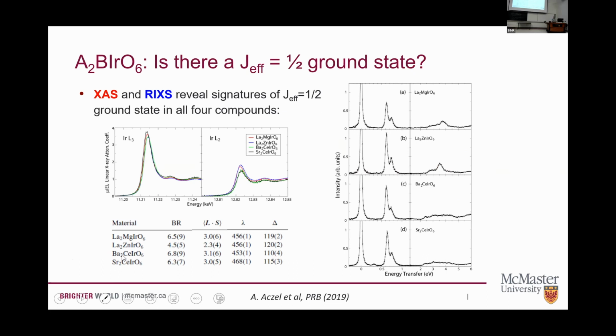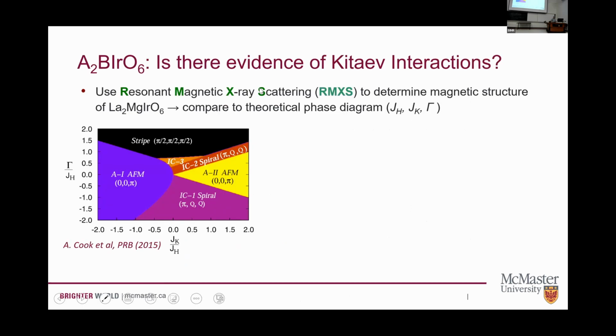So you can do the X-ray absorption measurements again, you can find the branching ratios, they're all very big. You can do the RIXS measurements. You can find that the crystal field splittings are small compared to the spin orbit coupling. So that's the lambda and the delta that we pull out here. And so these are signs that this J effective 1/2 ground state is a good description for all of these materials. And then we can look at the magnetic structure. So here, the energy scales are low enough that we can't really do magnetic RIXS very well. So we need some other route to try and guess at the interactions. And so what we can do is try and get at this indirectly. So we can solve the magnetic structure and then compare it to theoretical calculations.